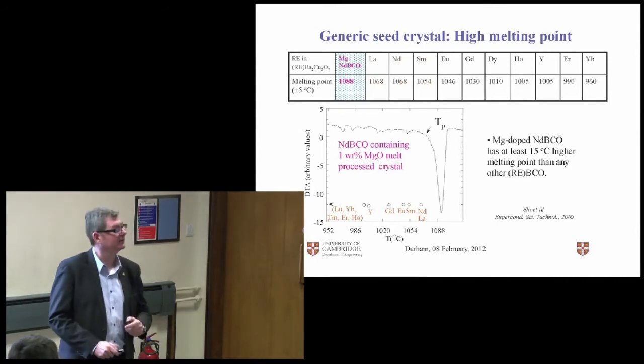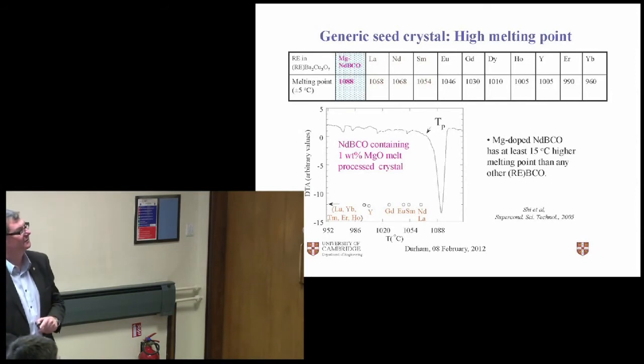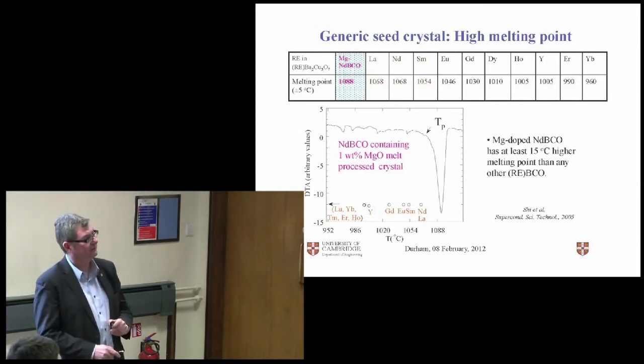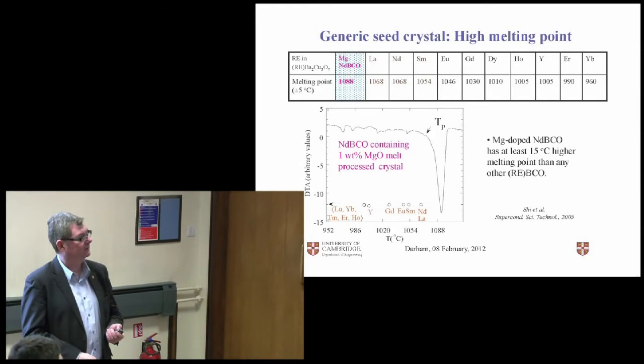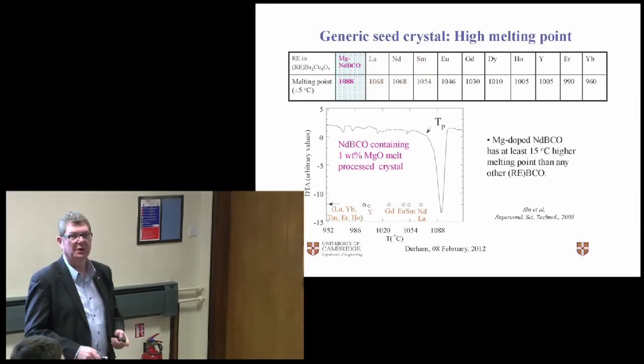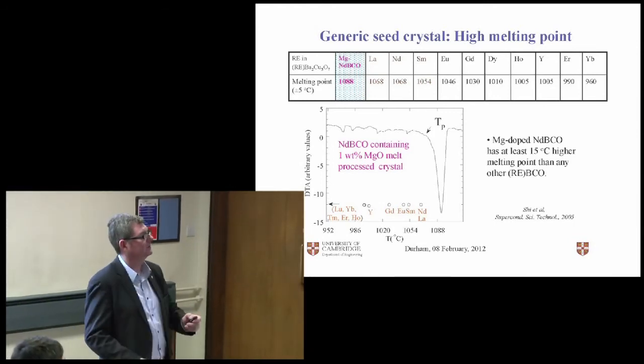It was a carefully designed experiment, and she deserved to find this material. So this is now patented, but it gives us this 15-degree window of processing where we can seed and grow a single grain.